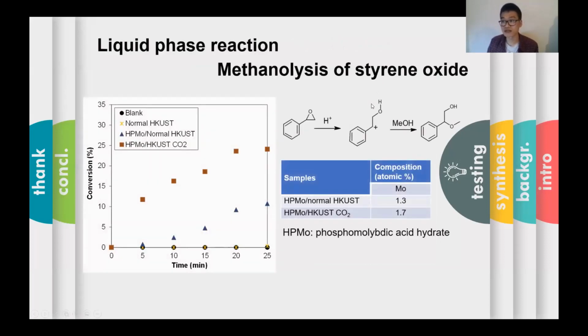The positive effect of introducing macroporosities to HKUST on the catalytic activities is expected to be greater in the case where the diffusional barriers are greater. Therefore, we compare the performance of the hierarchical HKUST materials in a model liquid phase reaction involving larger molecules to determine if this is indeed the case. So before the reaction, we encapsulate both samples with phosphomolybdic acid hydrate, which we call HPMo, which has an efficient particle size and a relatively small cluster size for this kind of reaction.